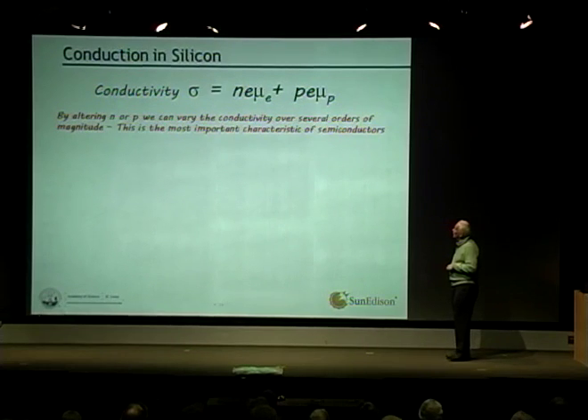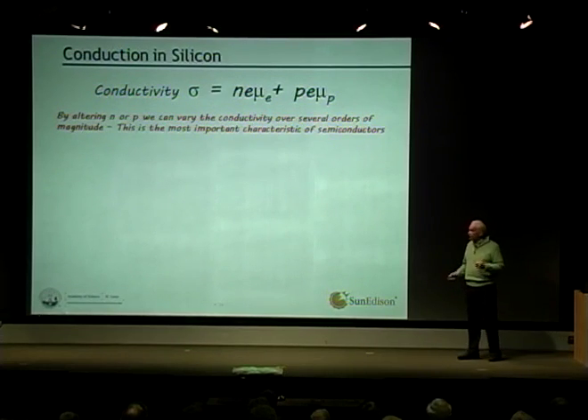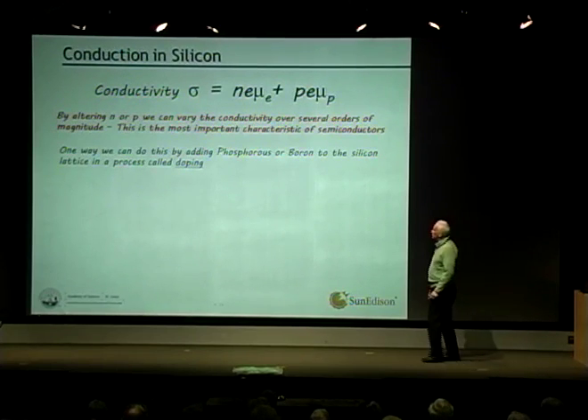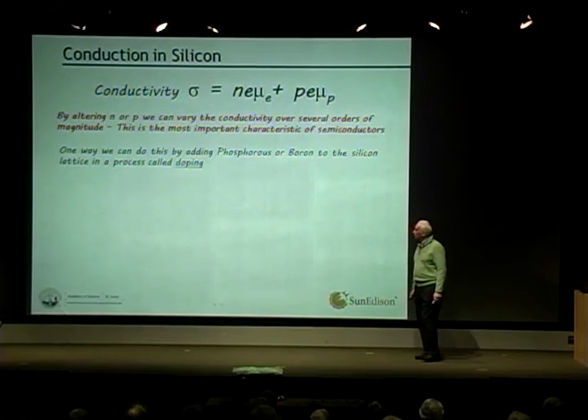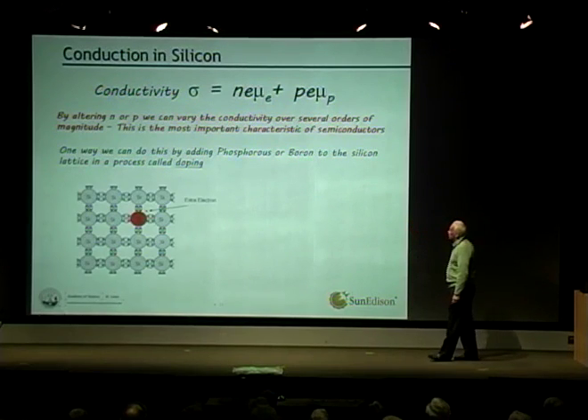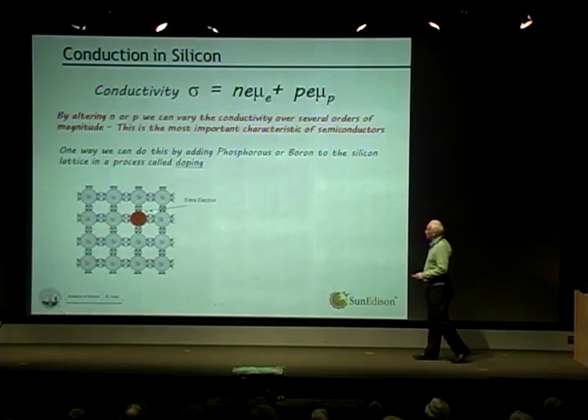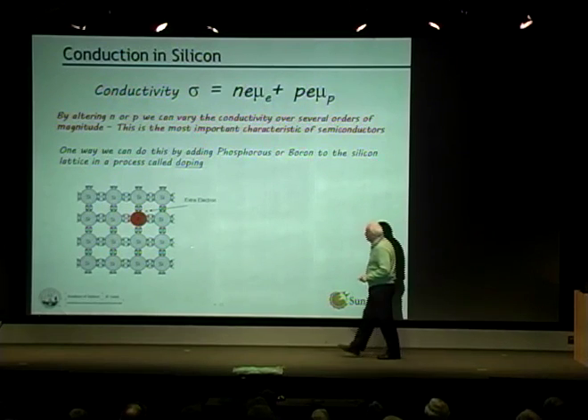If you can restrict the number of cars flowing, that's equivalent to changing the conductivity by changing the charge carriers here. Now, so how do we do this in practice? There are a number of ways, actually, but some very important ways for starting material in silicon is through a process called doping, and we do this in the crystal growth stage. We can add an atom like phosphorus.